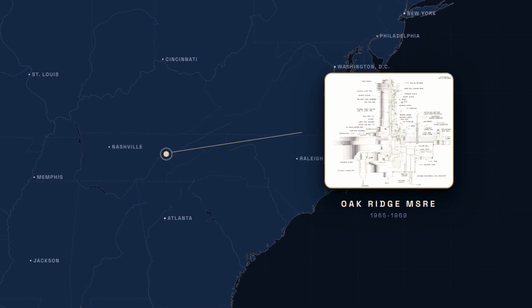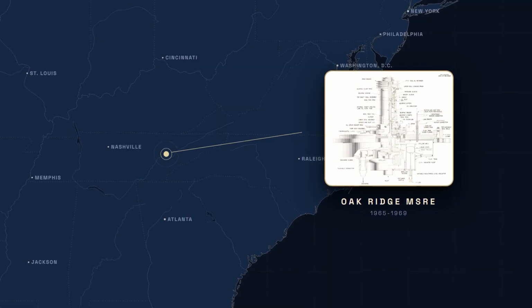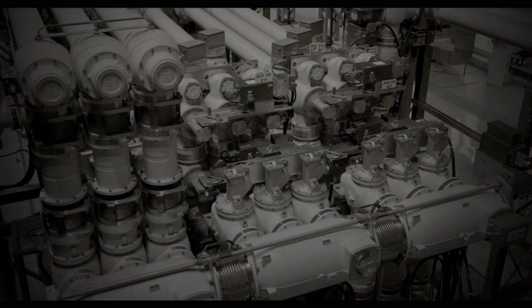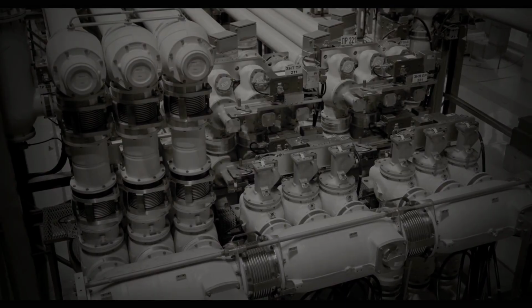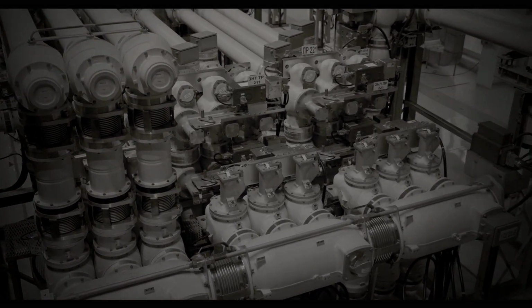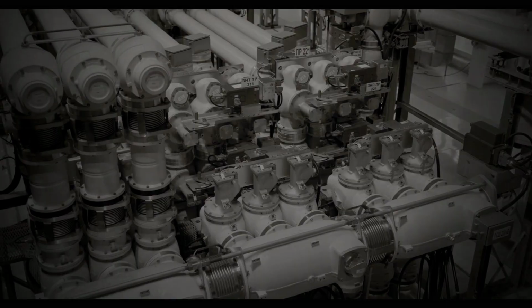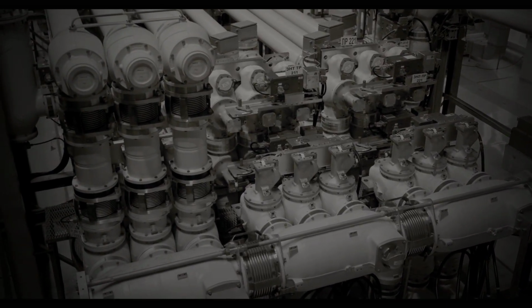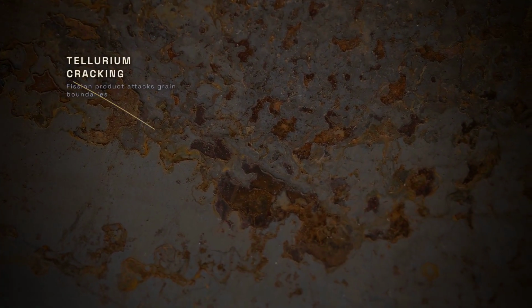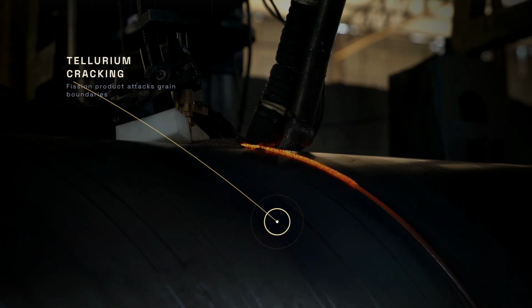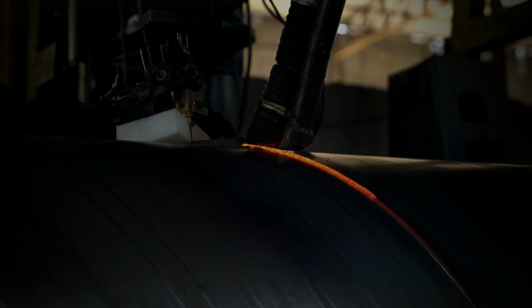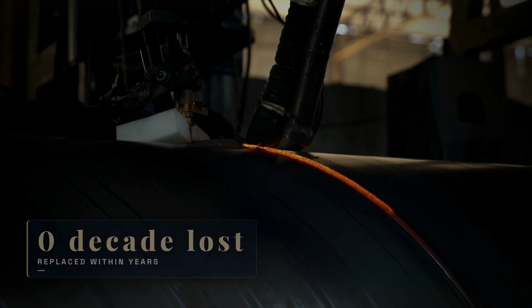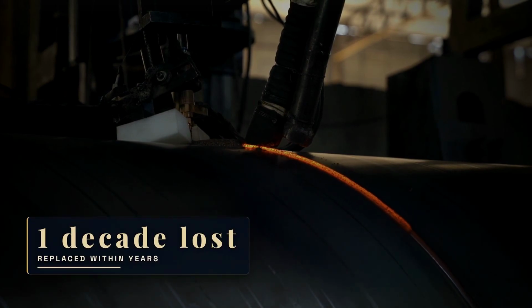Engineers there used a nickel-based alloy called Hastelloy N to build the reactor's piping, betting it could withstand fluoride exposure over the long term. Instead, fission product tellurium, generated continuously inside the circulating fuel, worked into microscopic grain boundaries in the metal and caused a specific failure mode researchers named tellurium cracking. Pipe walls thinned, welds became brittle, and components that should have lasted decades needed replacement within a handful of years.